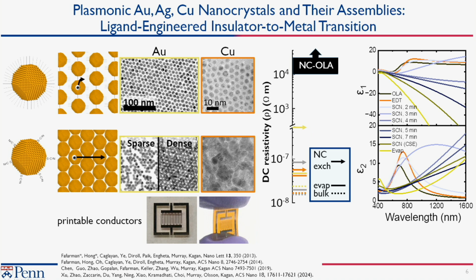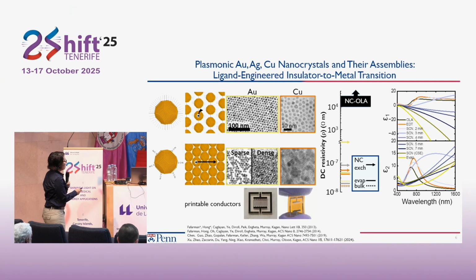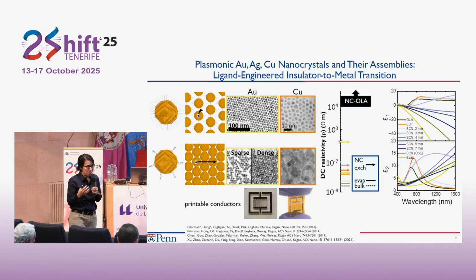And if you look at these materials, this is gold and this is copper, for example, and you measure their DC resistivity, it's above what you can measure, somewhere above 10 to the 4 ohm meters. It's very highly resistive. This is true in semiconductors from years ago as well. And what you can find is that these ligands, with a separation of 1-2 nanometers, act as a very good barrier to electron transport.